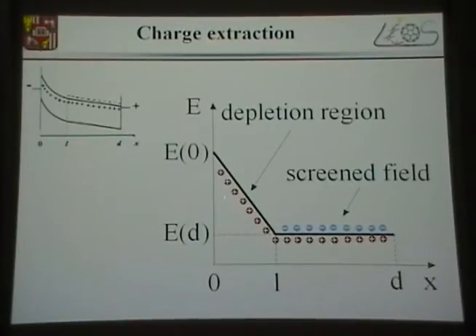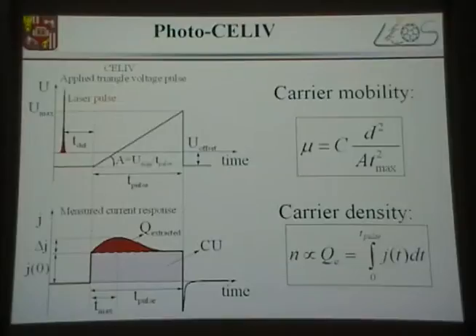I like this picture very much, you see? Those are the impurities, and those are the free charge carriers. So normally when you have those under normal conditions without applying anything, there might be some kind of Schottky barrier depending on the concentration of this dopant here. But what would happen if you start extracting the electrons, those uncompensated impurities would be left. Therefore, the charge neutrality would not be neutral. And actually, that's what you see in CELIV. If you look at the tails here, you also have tails with the charge carriers that are coming back.